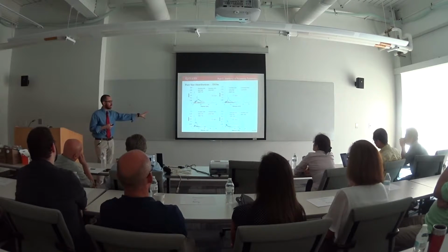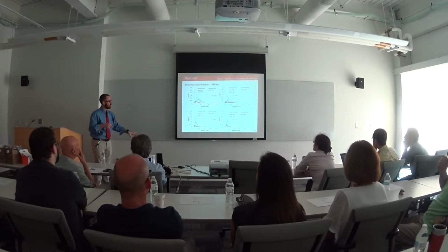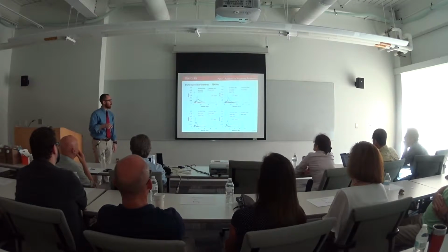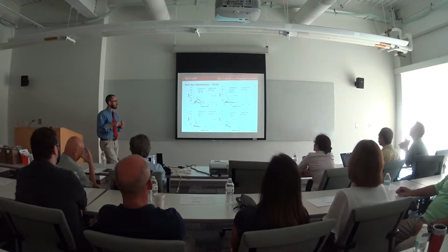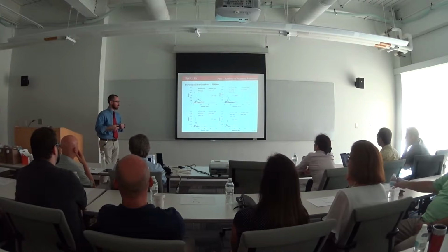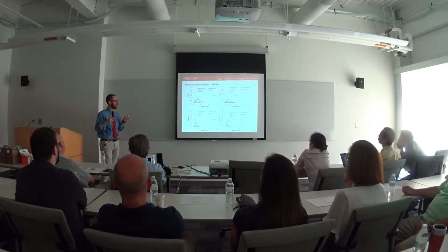A byproduct of all of these fractions of unfilled pores is that we can also describe pore size distributions of these materials. So this is a graph of 4 different samples. This is the pore size as a function of the differential volume. For these 4 samples, we had pores of different sizes from 10 up to 40 nanometers, and they're given by these pore size distributions here, which very accurately reproduce what was known experimentally. We can also describe the size fraction of the pore size distribution of the necks between the pores, and that'll land somewhere around one nanometer.